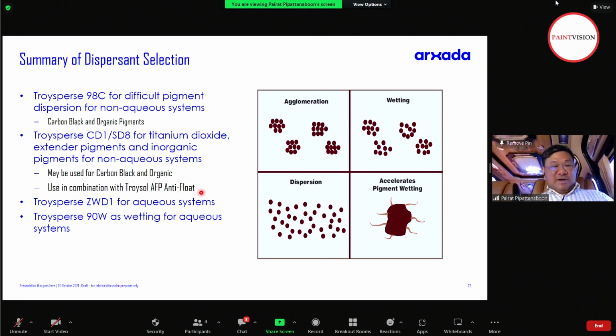You can use CD1 or SD8 together with AFP to control anti-float and anti-flattening in your formulation for solvent-based systems, particularly when you do alkyd paint and do in-plant tinting. ZWD1 is 100% active, a castor oil fatty acid derivative. You can use it in aqueous systems and also consider using it in epoxy or PU systems or TPA acrylic in your solvent-based system as well. And use 90W as a wetting agent for aqueous systems, right? That is the mechanism of dispersion and wetting when you do pigment dispersion.